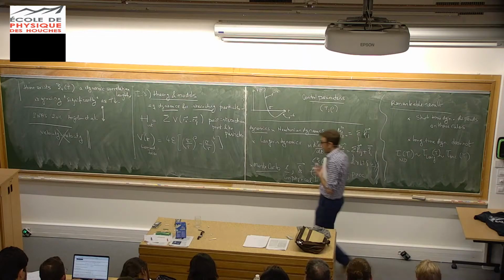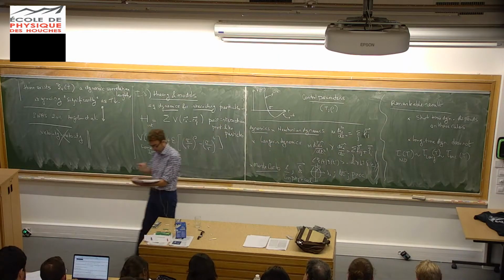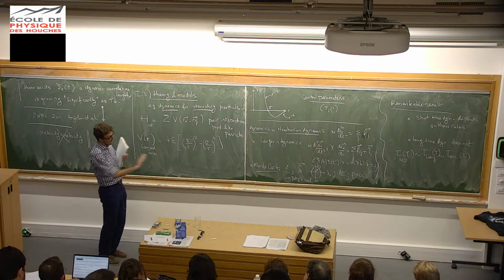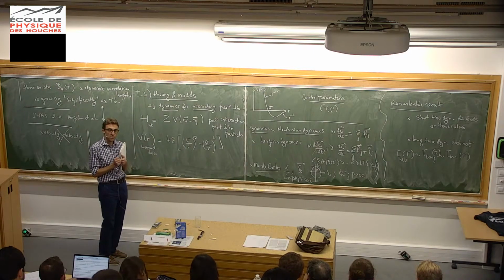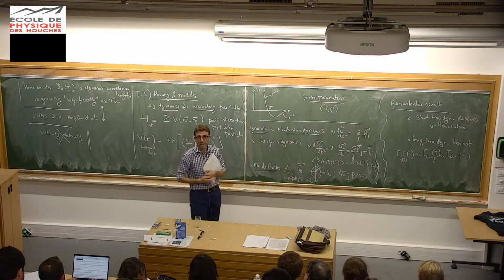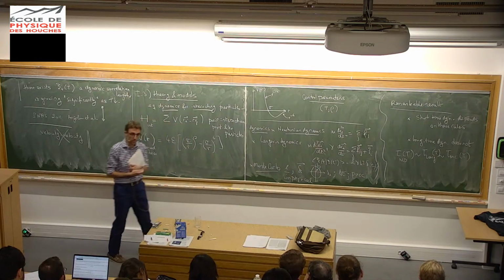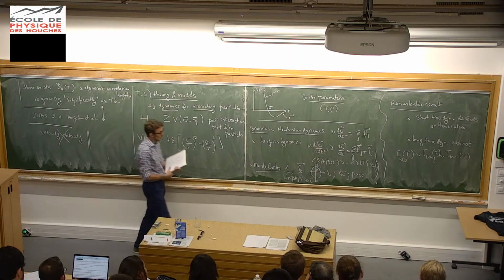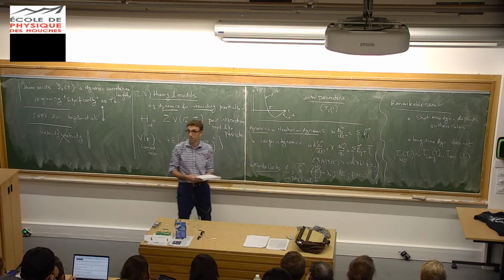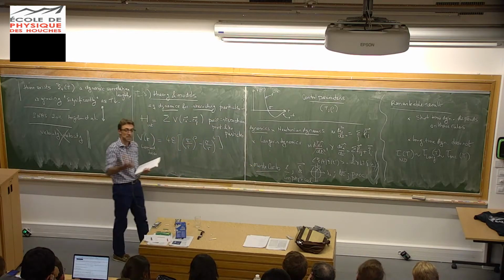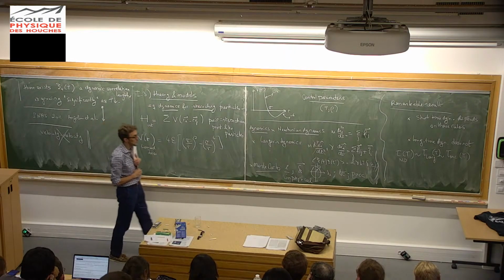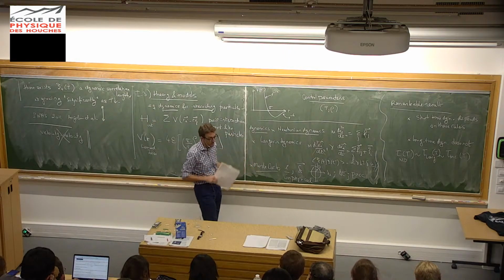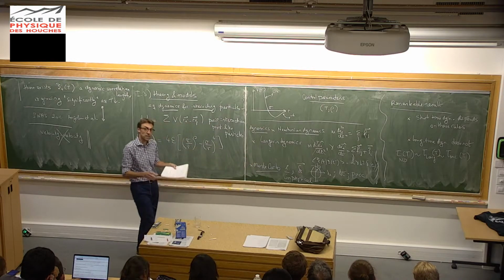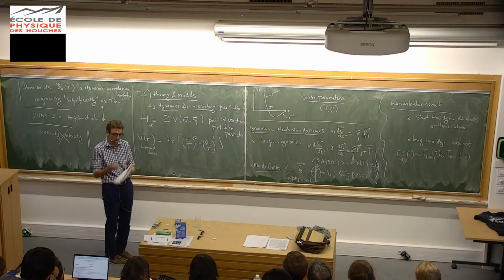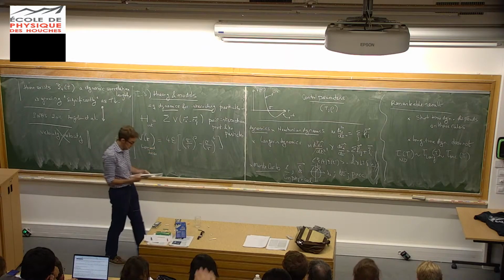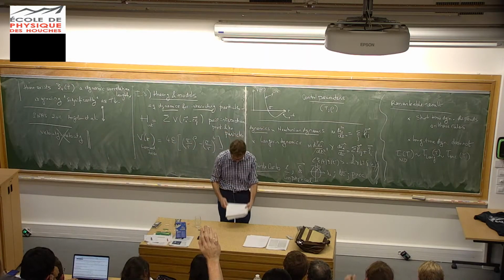So that's one of the key ideas I would like to tell: because of this separation of scales between what's happening at short times and the time it takes to build the structural relaxation, orders of magnitude slower, the details of how you're moving your particles at short distances, short times, they don't matter at all. The system will take the same route to move whatever the microscopic dynamics. And that idea of the separation of time scales results in a separation between the details at short times and what's emerging at long times. It will be a theme of these lectures.